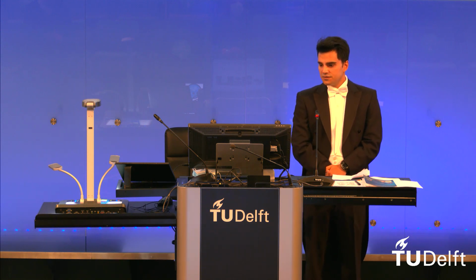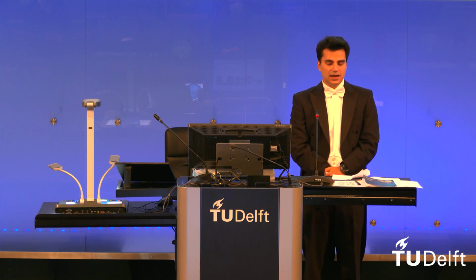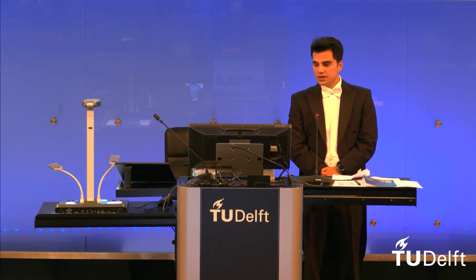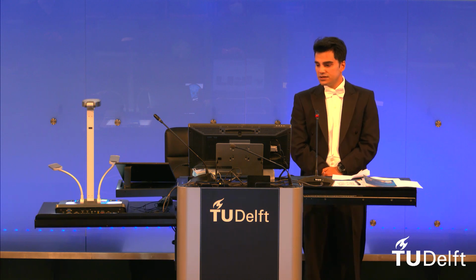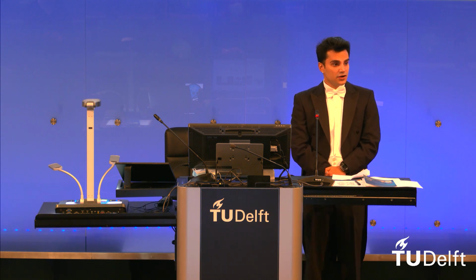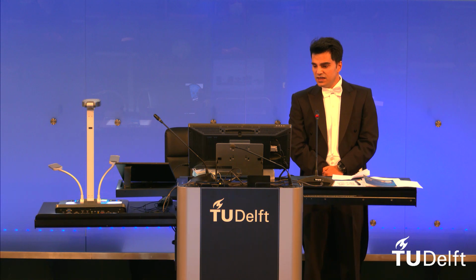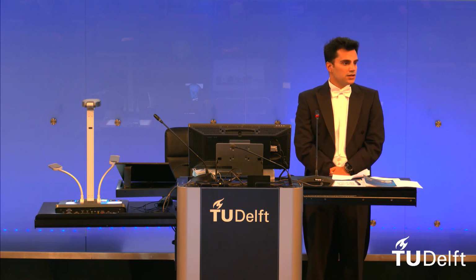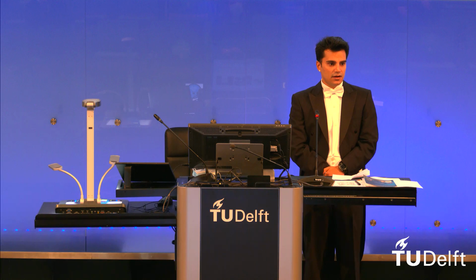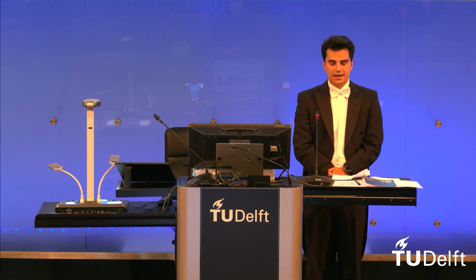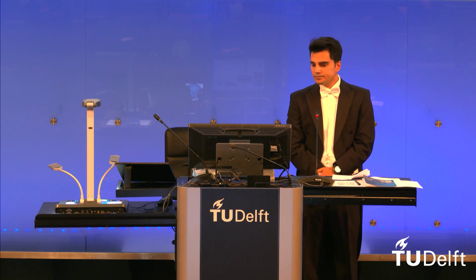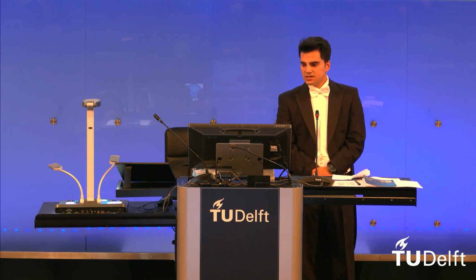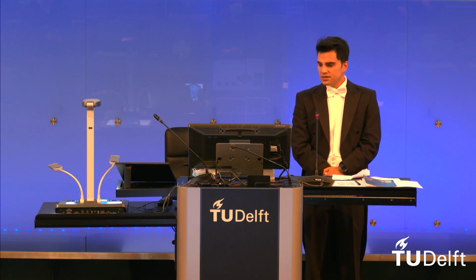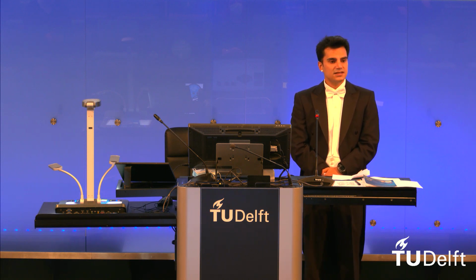We did non-destructive measurements on sample squat cracks, and we classified the orientations of the cracks, and we could determine their occurrence rates. And of course, we compared the results with finite element modeling computer simulations in order to see how comparable the results could be between the modeling and the CT scan, which are the real measurements. Here you see some definitions that we developed in this chapter in order to facilitate the characterization process.